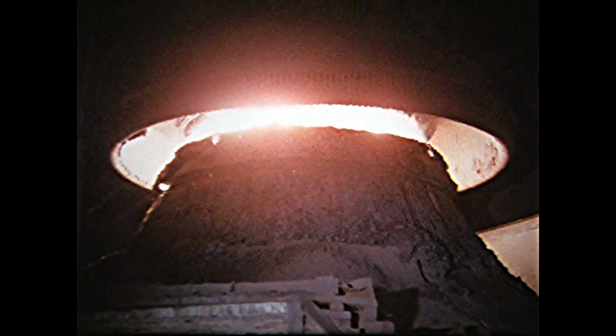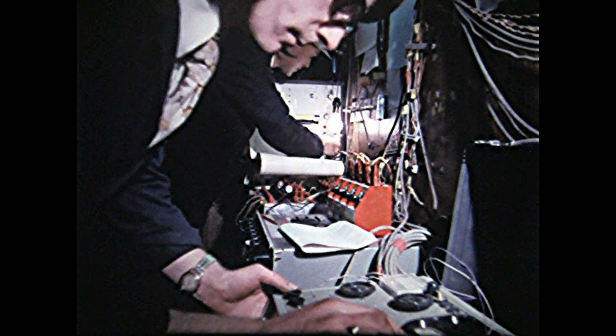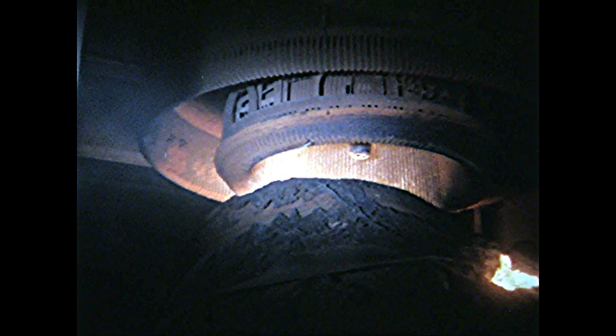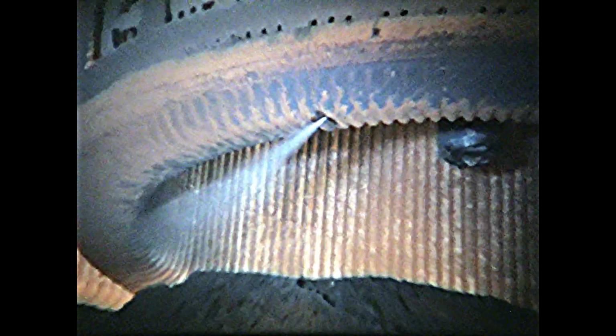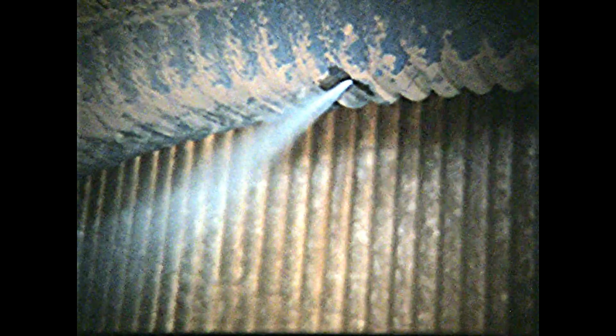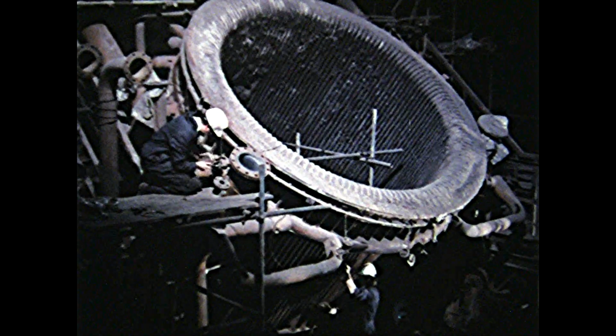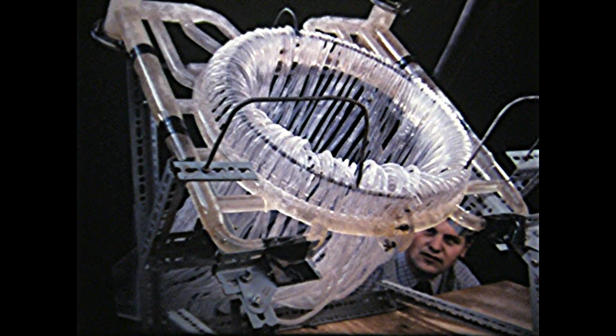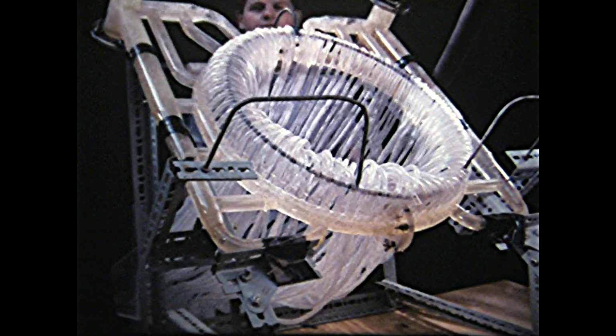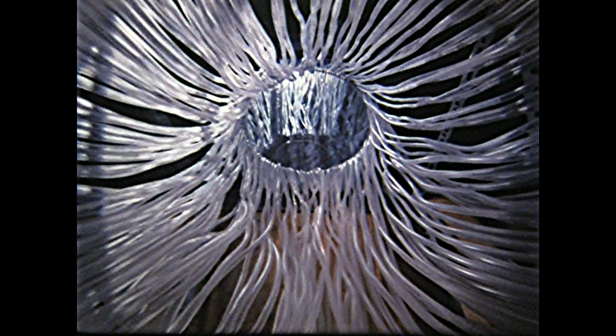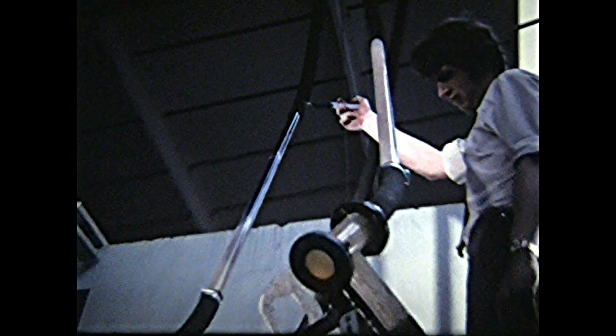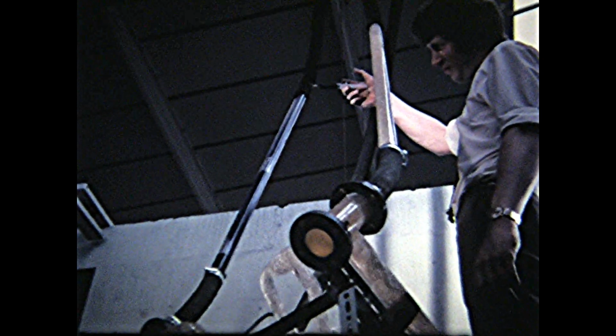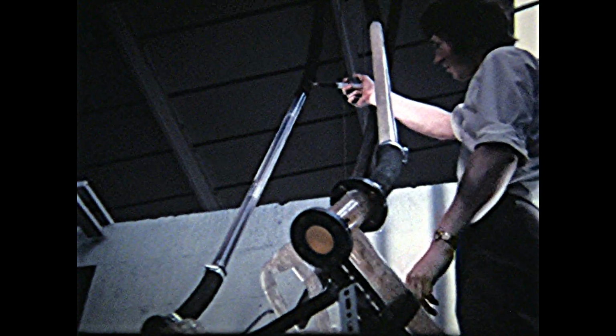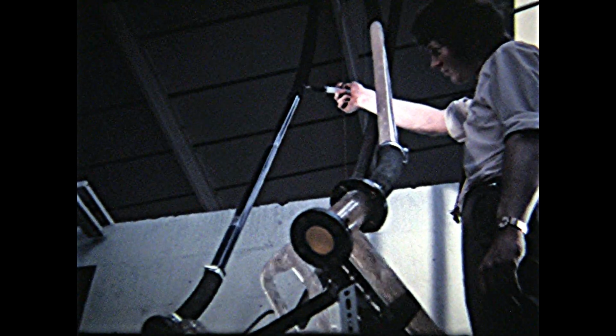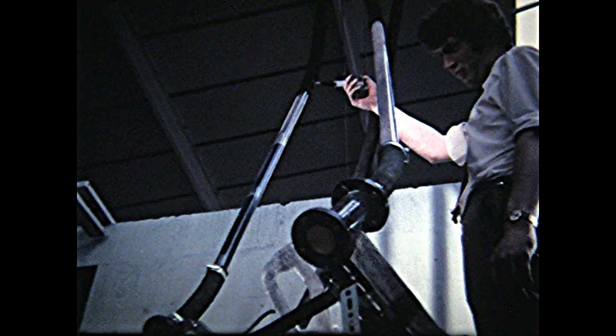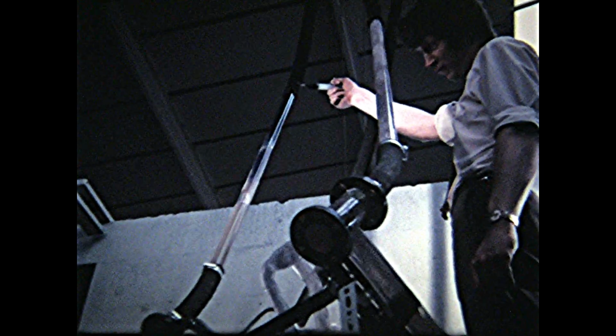A problem of a totally different kind cropped up when this steel-making vessel was being run in. It was found that some of the water cooling tubes in the hood were springing leaks. The tubes were being burnt through, but why? Within days, a scale model had been made with air bubbles simulating the circulation of water and steam. Injecting a dye showed that in the up pipe, where steam should have been rising, in fact, water was descending. Having discovered the fault, it was fairly easy to solve the problem and get production going again.